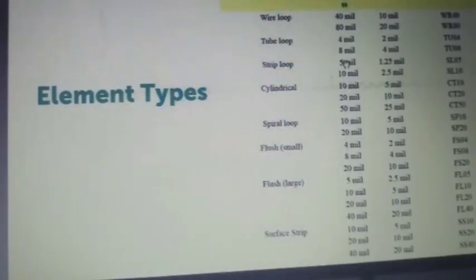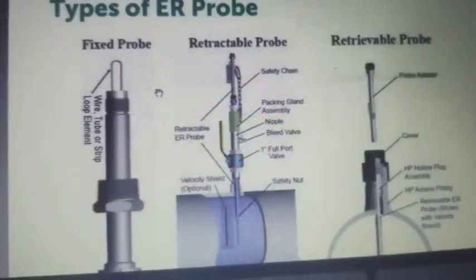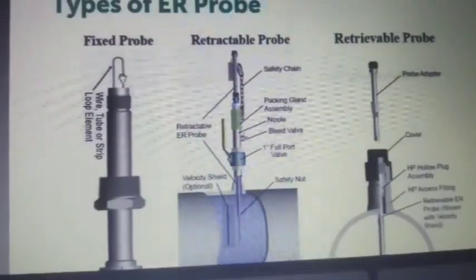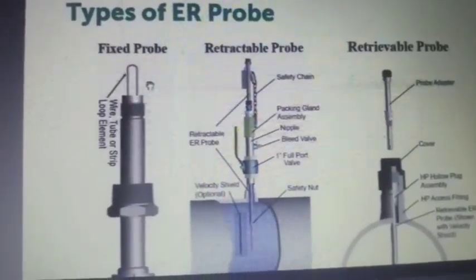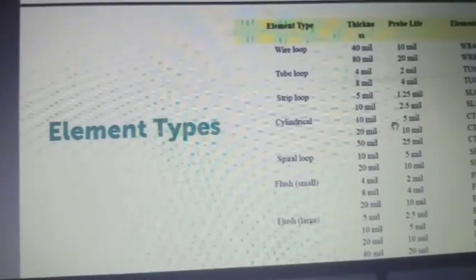But on the contrary, a high sensitivity probe means you will get the corrosion rate instantly, but the life is half. If you have 4 milli inches thickness, when it becomes 2 milli inches, you cannot use it further. After 2 milli inches, it will corrode faster and then the probe will have discontinuity. The probe will corrode and then the circuit will break, and then it will not pass a signal. So when the probe size goes from 4 mils to 2 mils, you have to change the probe. Whereas with the surface strip, like 10 mils, you have a longer life.